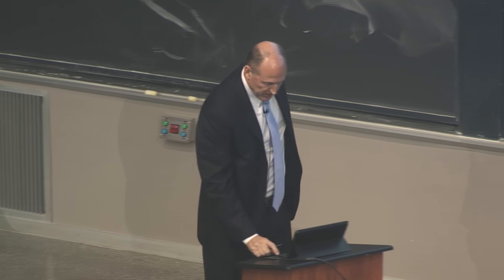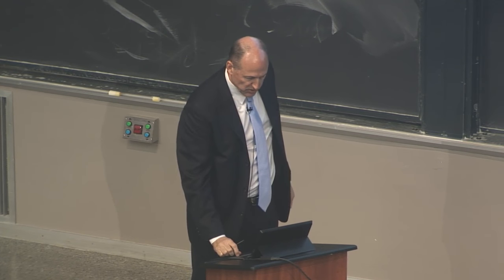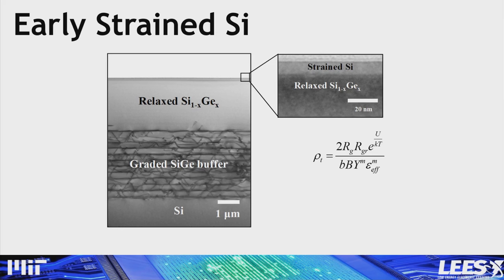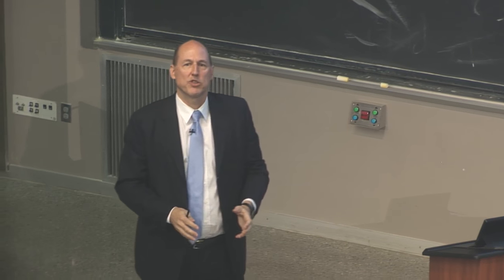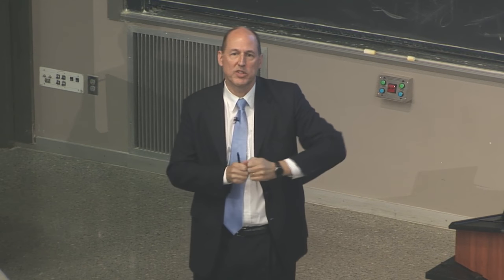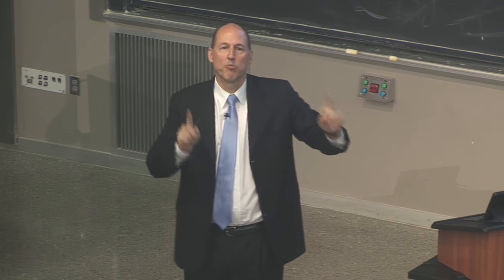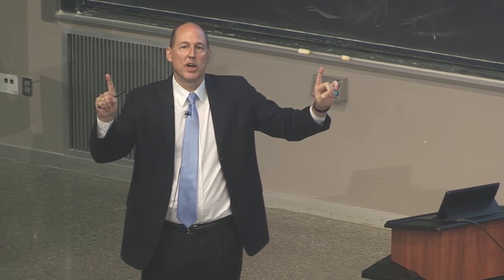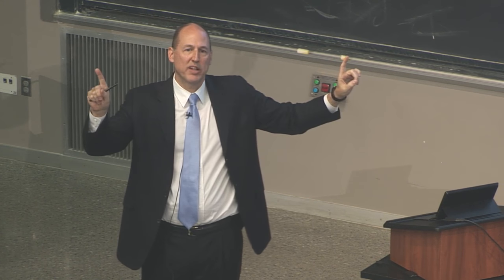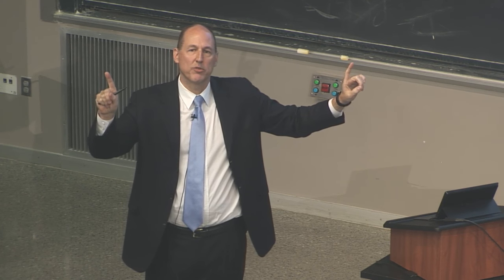And it turns out that it was an amazing result. What you can do is do what I'm showing there. You can create these layers, and all those black lines are dislocations. You can have massive relaxation, tons and tons of misfit dislocations being formed, but relatively few actual threading dislocations passing through the material to do this, right?